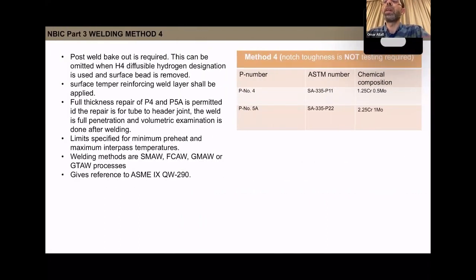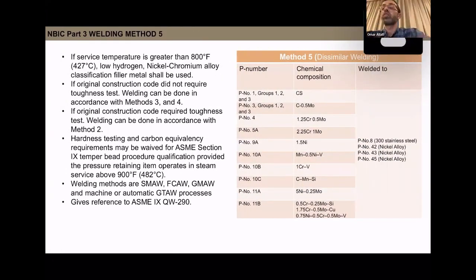Method 4 is mainly for P-number 4 and P-number 5A, and this is without impact toughness. So yes, they give reference to QW-290, and again, full thickness repair, similar to method number 2, is permitted for tube to header joints. Post-weld bakeout is required and can be omitted when using H4 and the surface bead is removed. Welding method number 5 is for dissimilar welding. The P-numbers listed here are for the base metal, which can be welded to P-number 8, like 300 series stainless steel, or any nickel alloy, P-number 42, 43, and 45. So this is for dissimilar.